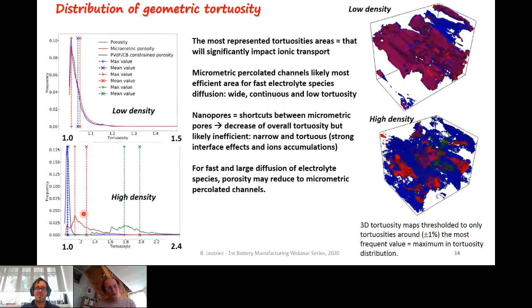But what is surprising at first sight, looking at the result at first glance, is to see that the tortuosity of the total porosity is lower than the two others. It is not a mean value. So this can be better understood when you look here at these 3D tortuosity maps. They've been obtained by thresholding to tortuosities around plus or minus 1%, the most frequent value that corresponds to the maximum there in the tortuosity distribution.